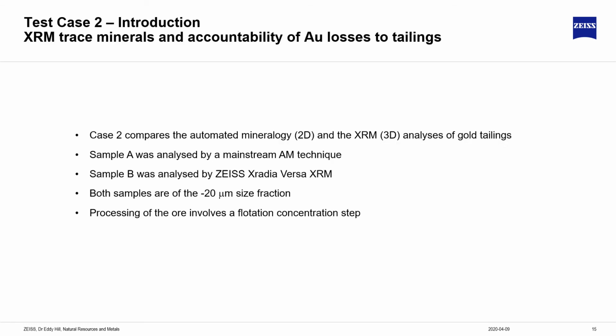Test case 2 is slightly different. In this case, we compare the automated mineralogy analysis performed in the past for the mine to an XRM 3D analysis of the gold tailings. Sample A was analyzed by mainstream automated mineralogy techniques, but sample B was analyzed by ZEISS Xradia Versa XRM. Both samples are of the smaller than 20 micron size fraction, and processing of the ore involves a flotation concentration step.